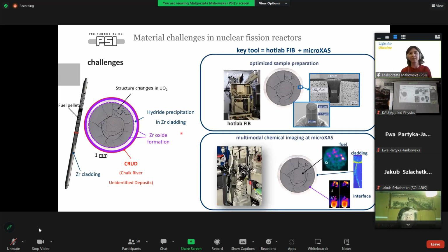To prevent them, what we do at PSI is we have a special FIB, which is placed in a hot lab. It's a FIB that can produce small, tiny samples from highly radioactive materials. So we can extract a pillar even from a spent fuel, which is itself very highly active. But when we downsize the sample, then the activity is not so high.